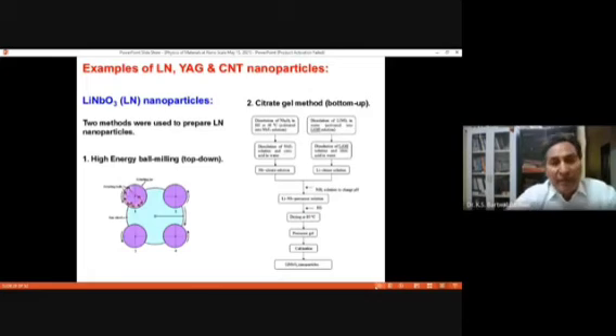Now, I'll give 2-3 examples of materials which we have developed in our laboratory here in RRCAT, so that you can get a feel for how these nanoparticles are made. I have taken the example of lithium niobate nanoparticles, and I'll show you both the top down and the bottom up techniques. Top down is basically: we take a lithium niobate single crystal or polycrystalline bulk, and crush it in a high energy ball mill, so it becomes nano-sized lithium niobate.